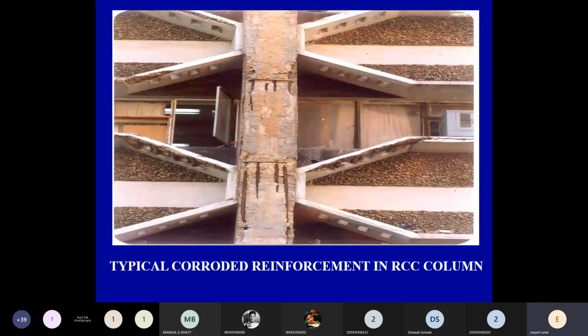This structure was supposed to sustain for about 45 to 50 years, but somehow within a span of 8 to 10 years, the condition is like this, and because of this the structure is now not in use. So it's a typical case of poor construction, poor detailing, and poor quality control at site.